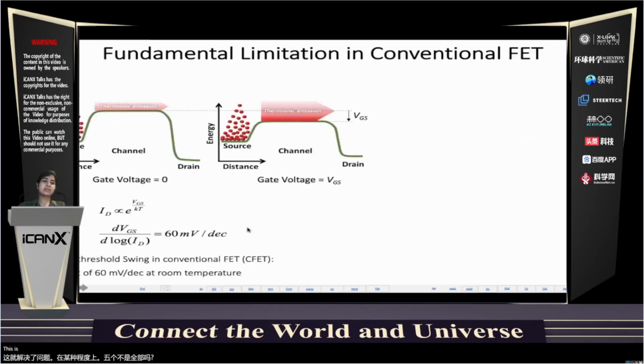This is because as far as the power goes, we have a fundamental issue here. And I can explain it with this schematic here. So suppose at the off state of the transistor, you have a certain barrier height of H. But when you apply a gate voltage of VGS, say the maximum amount by which you can lower the barrier would be similar to VGS. You cannot do better than that. And assuming this is in units of electron volts, that's the best case by which you can reduce the barrier if you apply a certain gate voltage of VGS.